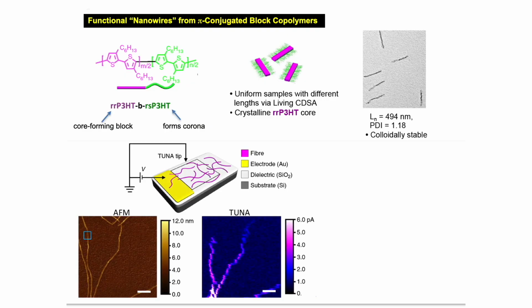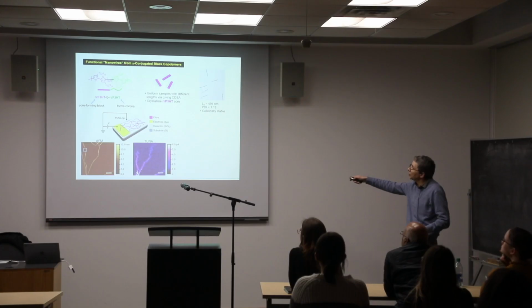And then you can use methods to actually look at individual fibers, and you can measure the current along a micelle. This is the tunneling current along these micelles. These are fiber-like micelles that we place on a surface, and then we use this method where we use a tip that can measure the current between the tip and the substrate, which is gold, and you can see the tunneling current. So these really conduct electricity.